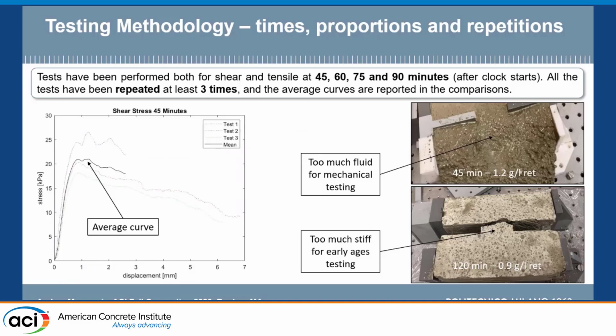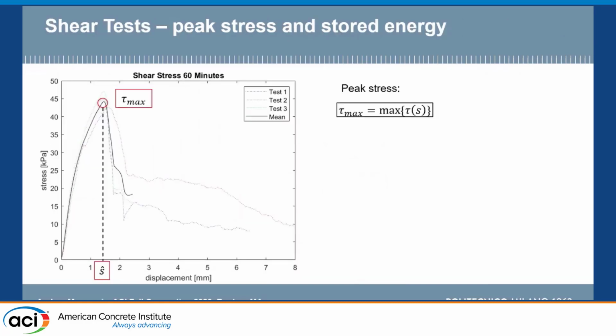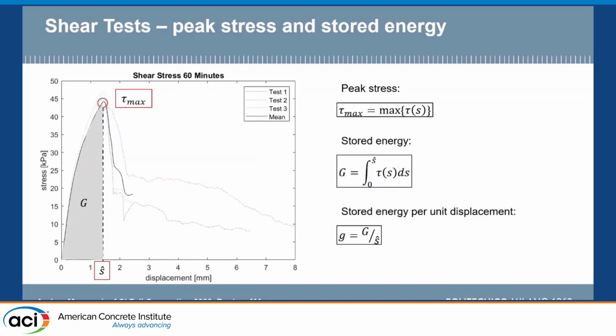And then we have averaged the curve because we have tested at least 3 times at each testing time for each mix. So this is an output of the shear test curve. For example, here at 60 minutes, we are particularly interested in the peak stress and also the stored energy. That is, as you can see here, the area below the curve until the peak stress. To make it independent of the displacement, we have divided the value of the energy by the displacement corresponding to the peak, so obtaining a stored energy per unit displacement.